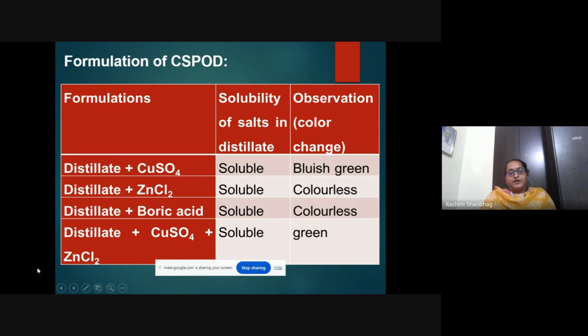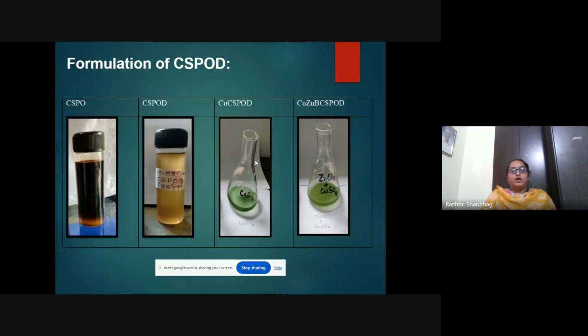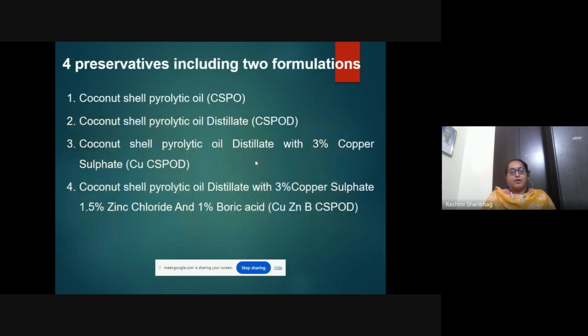The original liquid was a viscous black color. The distillate was colorless, and we had to check the solubility. After the solubility of this particular component, the inorganic salt, it converted into a bluish green or colorless liquid. The best one was copper sulfate along with zinc chloride. So this is how the formulation looked after the mixing of the inorganic salt. In true sense, we actually prepared two formulations, along with which we used the coconut shell pyrolytic oil distillate.